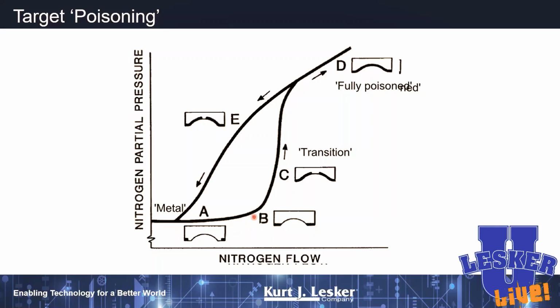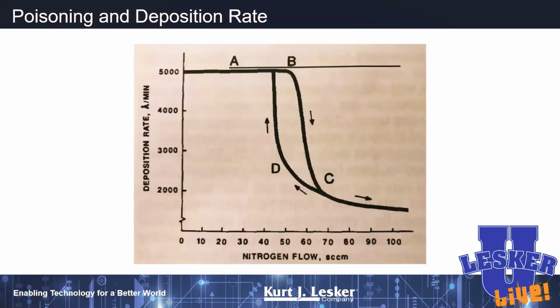But as we increase that nitrogen flow, and we might have to do that in order to get the stoichiometry of the titanium nitride that you need, we get more and more redeposition of the nitride back on the surface of the target. Notice the slope of this curve here, very, very tough to control on that slope. So if we get too much redeposition of the nitride on the surface of the target, now we're essentially sputtering a nitride. And so we don't get the benefits of the metal deposition rate that we want. There's a couple of really nice sophisticated control mechanisms out there that we can use to control nitrogen flow rate so we don't see this transition. If we had more time, we'd chat about it. If you look at just deposition rate here on this axis, just notice that we get the deposition rate that we want from metals, but then suddenly it collapses pretty dramatically to the deposition rate, let's say, of nitrides.